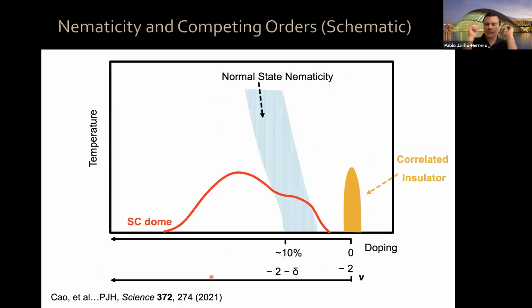So this picture that is emerging, this nematicity and competing order joint schematic picture, is the following, okay? In the phase diagram of magic angle graphene, temperature versus doping near the region of filling factor -2, 2 holes per moiré unit cell. So at -2, so 0 doping, we have a correlated insulator behavior. Then we have a superconducting dome, okay? The superconducting dome experiences a depression at a doping of order 10%, okay? And that depression here coincides with a normal state resistivity ridge, okay? Which, if you suppress the superconducting dome, leads to an insulating state here, okay?